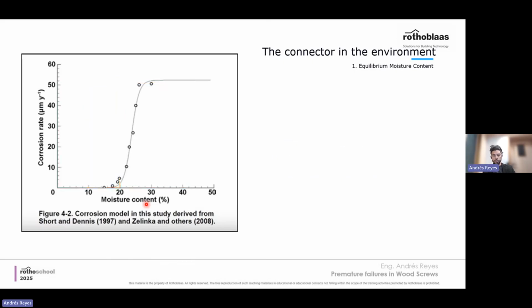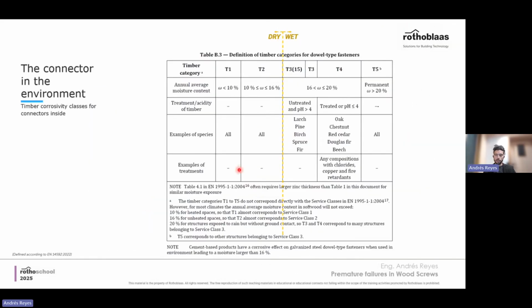And I will get back to this slide just to give you an idea. Above 20%, and 20% is not that hard to reach on many construction sites, the norm tells us that the environment is very aggressive. So it is a T5 when above 20%. And just to give you an idea, in T5 conditions, for design, the norm prescribes that you should use stainless steel A4.